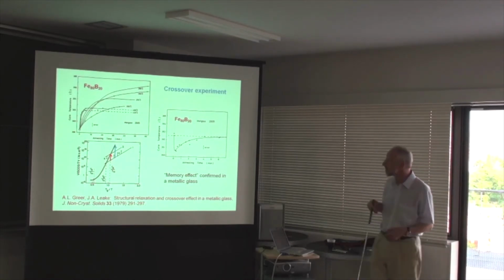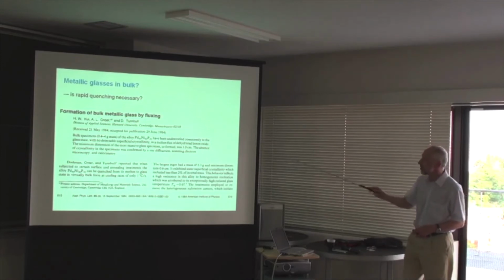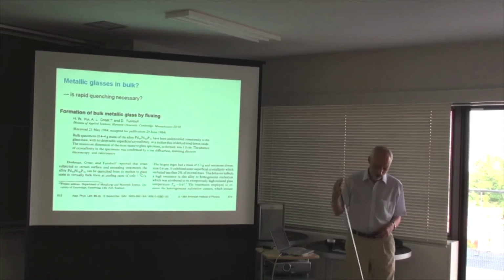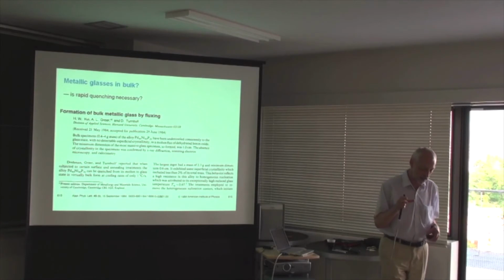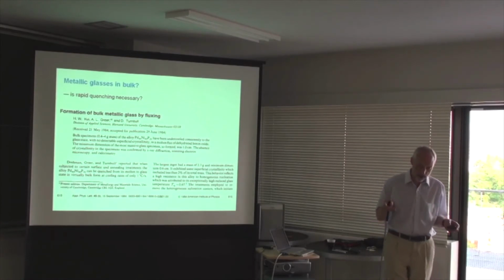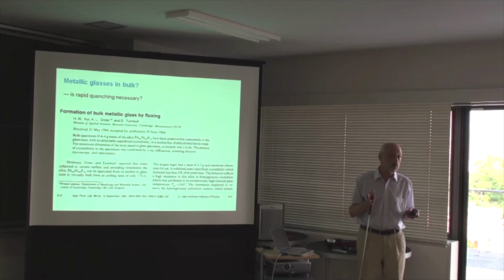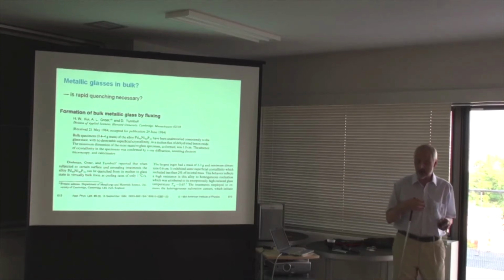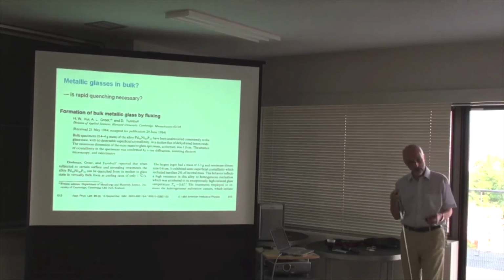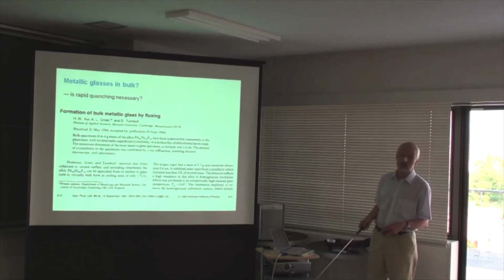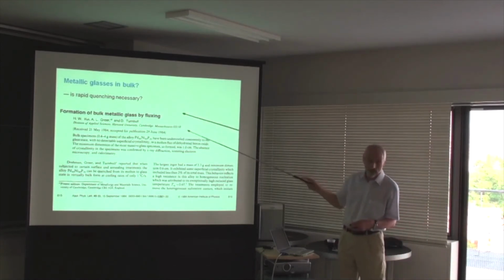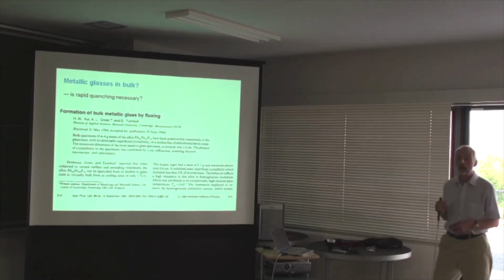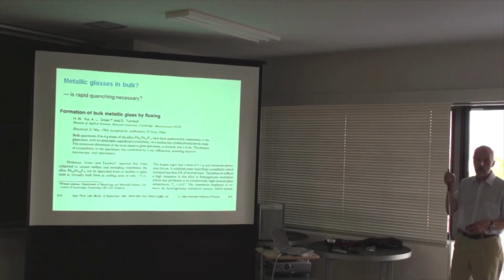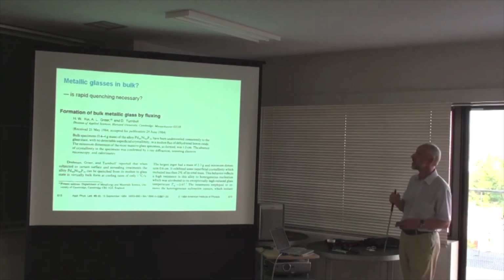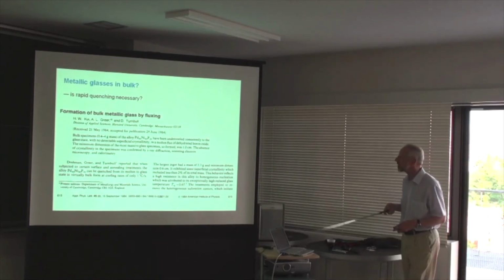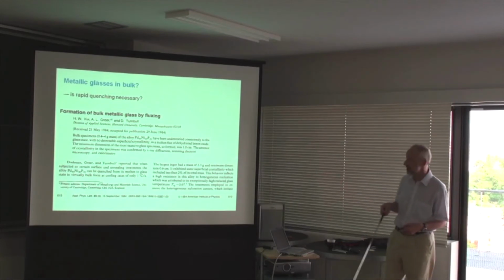And the other thing, of course, you'd like to do is have a glass that is not in such a tiny amount. And David Turnbull was interested in processing of materials, and he had the idea that you use fluxing, coating in a liquid oxide, which turns out to be very useful in processing some semiconductors like gallium arsenide. What would happen if you used the same idea for a metallic glass forming composition? It turns out it's extremely successful, and you can clean up the liquid metal, take out the little bits of dirt, if you like, that nucleate crystals, then it becomes much easier to make a glass. And this was up to a size of about 1 centimeter.